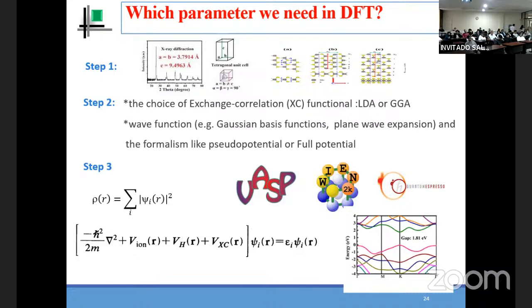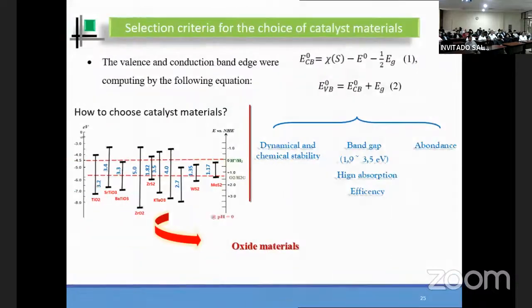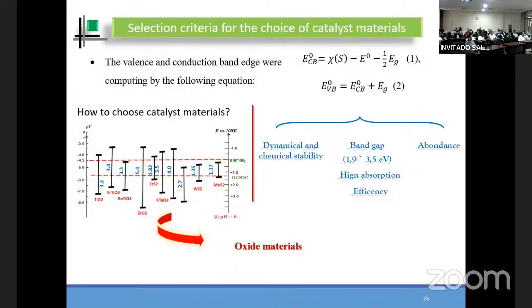The formalism of the pseudopotential is implemented in the two codes, Quantum Espresso and VASP, and the full potential is implemented in WIEN2k. So step 3 is to apply these parameters to compute the density of states and to search the energy levels of this system. And we get the band structure of this system, and we can describe many more properties of a system. So for photocatalysis application, we are also looking for the band gap and the band edges, like the valence and conduction band. They are computed using this formula.